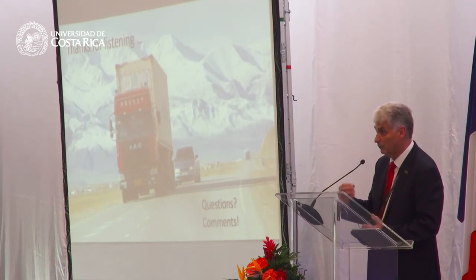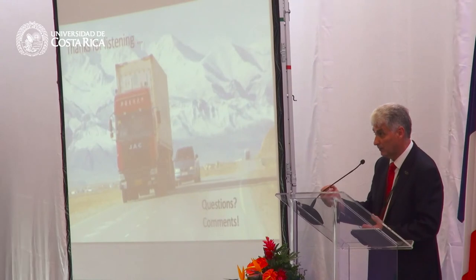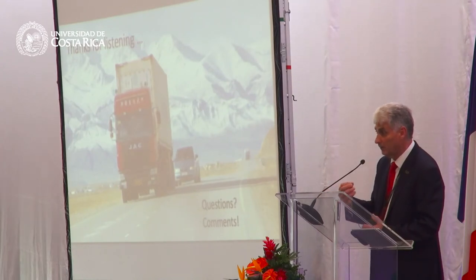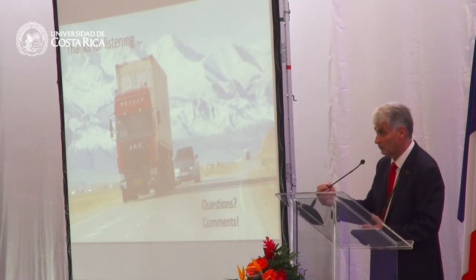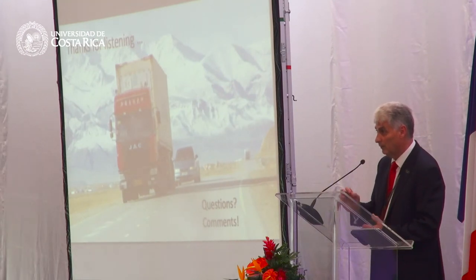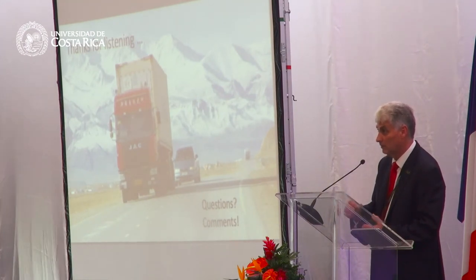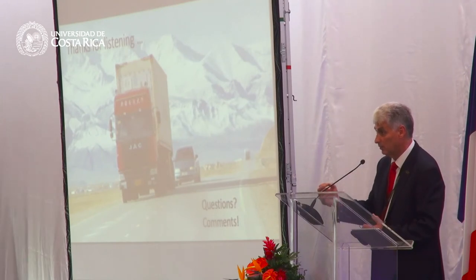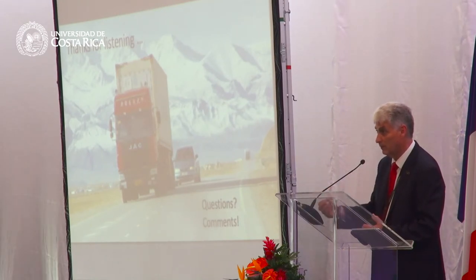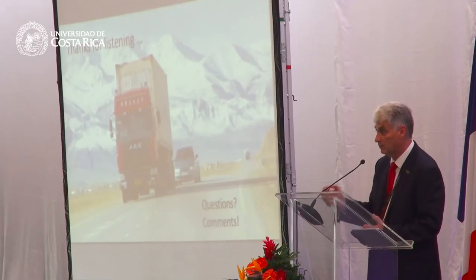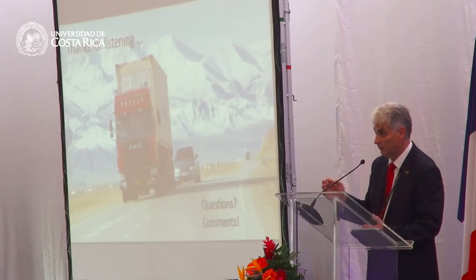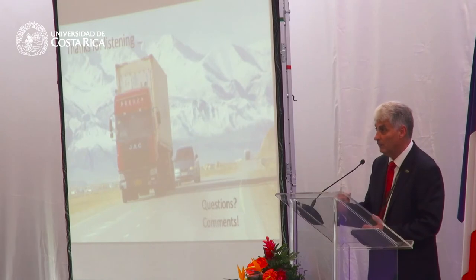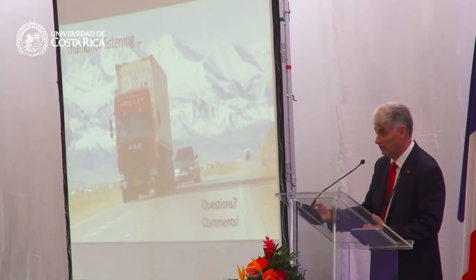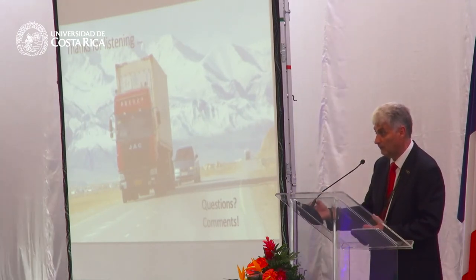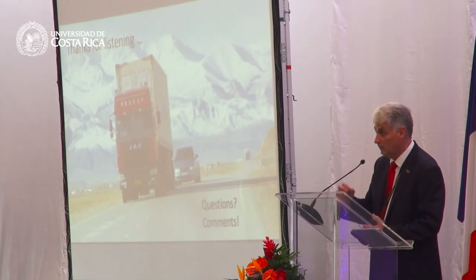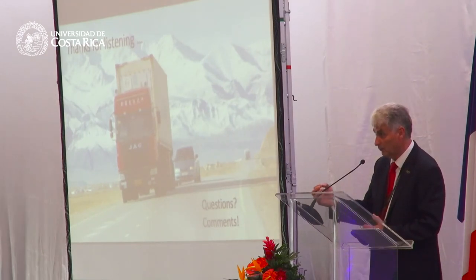They use that for chip seals or surface dressing binders, and that's something that is used in the industry. In the US, we have been exploring various tests, things like the double-edged notch tension test, and there are several other tests, to try to define the failure condition of the asphalt binder. We haven't really fully developed those procedures yet, and we don't have a test for doing that. But this is something that's needed in addition to the linear viscoelastic parameters.